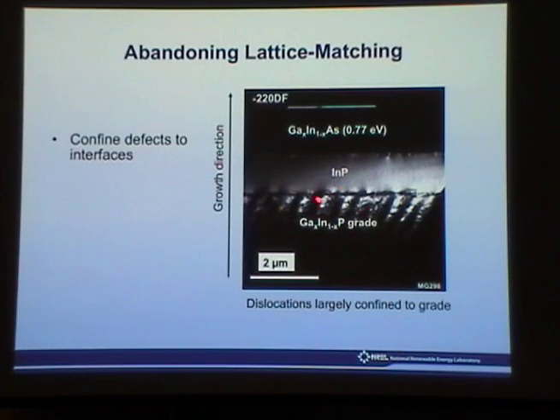There are some defects at the interface, but the material quality of the indium phosphide and of the gallium arsenide, you'll have to take my word for it, because you can't see it on this projection. But the material quality is very good. There are very few dislocations threading their way through these two materials. So what we've done here is engineer a grade that changes the lattice constant and achieves our aims. It relieves the strain, and it does so keeping the dislocations within the layers of the compositionally graded buffer and not in the active material.